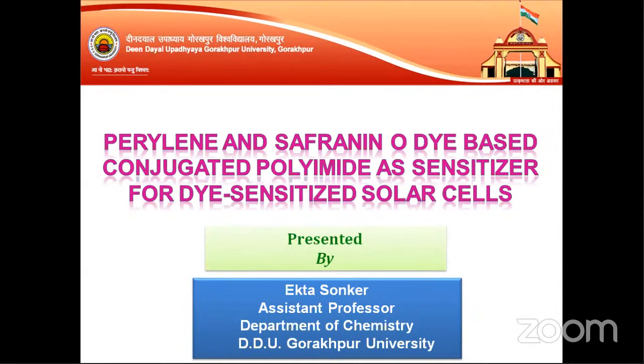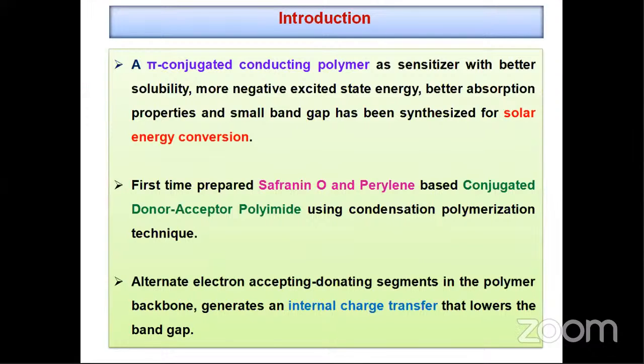Now, this conjugated polyimide means the polyimide backbone must contain alternating single and double bonds so that upon doping with some dopants, charge carriers can be generated in the polymeric backbone, and the movement of these charge carriers along the polymeric backbone will contribute to the electrical conductivity of this conjugated polymer. Now, here I am using an organic monomer for the synthesis of this conjugated polymer, which is photochemically stable, and they show strong absorption and emission properties.